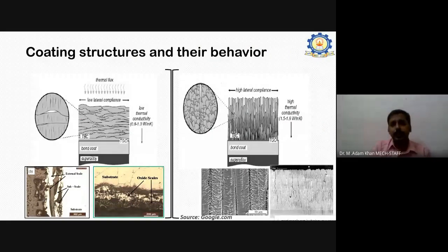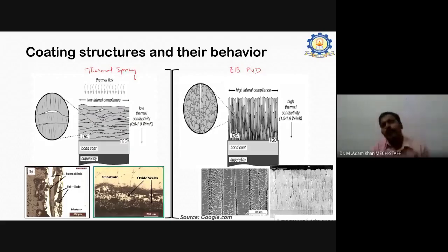So for the thermal spray method, this is how it has been done, and this is how the electron beam PVD method has been done. In the thermal spray method, you can see the structures in the form of splats. At the same time, here you can see the structures in the form of columnar structures. That is the first and foremost difference. Second, the heat energy or the energy facing the environment has to travel through so many layers. You can see layer 1, then it has to cross it like this, then cross again. So it has to travel so many paths from the top towards the bottom, through so many layers and structures. After that, it has to reach the adjacent layer called the bond coat.